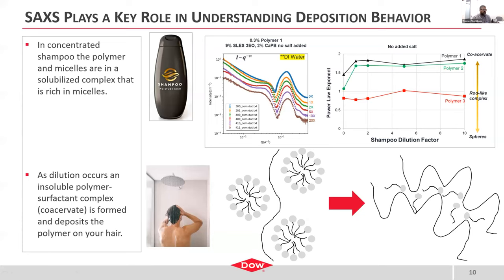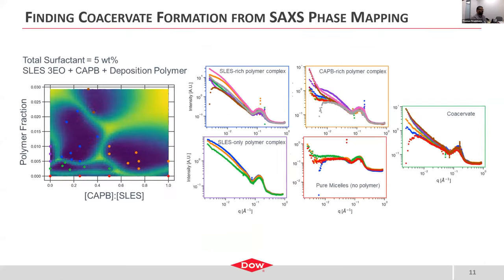However, in the third polymer system, we didn't undergo a coacervation event. So this is a new chemistry that we were looking at, and we needed to understand how can we get this coacervation event to occur if we wanted it to occur, or where were the regions of phase stability in this sort of a formulation. So what we were able to do was use our high throughput formulation capabilities here at Dow, combined with the high brilliance of the synchrotron beam, combined with machine learning algorithms from our collaborators at NIST to map the phase behavior of this surfactant polymer deposition map.